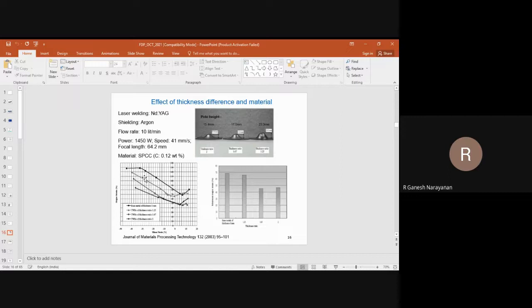One, on the whole, if you see, base metal has got better forming limit because there is no weld at all. It's one sheet of 1 mm thickness. And it's quite sensible and logical to expect that. But if you want to make tailor welded blanks for the known advantages it has got, you need to reduce the thickness ratio, because if you reduce the thickness ratio, the forming limit approaches that of the base sheet, and that's what we want, right?